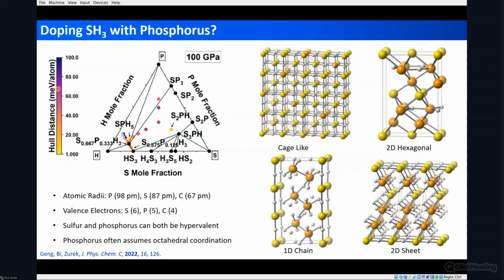But what it does say is that it is not a bad criterion for deciding which structures could potentially be synthesized in experiments. So we focused on studying a number of these systems that were within this potential synthesizability zone. And there were a number of different families found. Sulfur here is yellow, phosphorus is orange. Some of them have these 2D honeycomb hexagonal networks. Other ones have 2D sheets, 1D chains, and then also cage-like systems that could be related to the parent SH3 compound, except with phosphorus substituting one of the sulfur atoms.